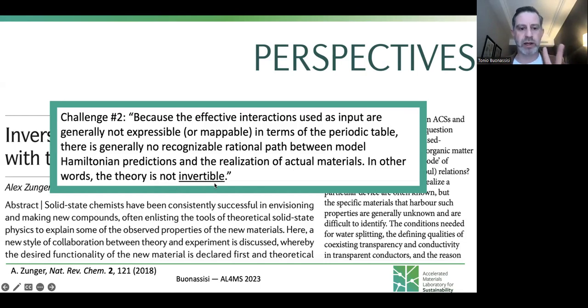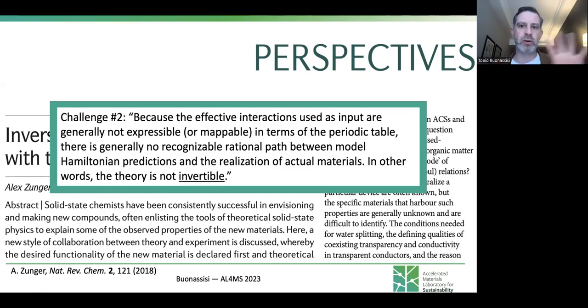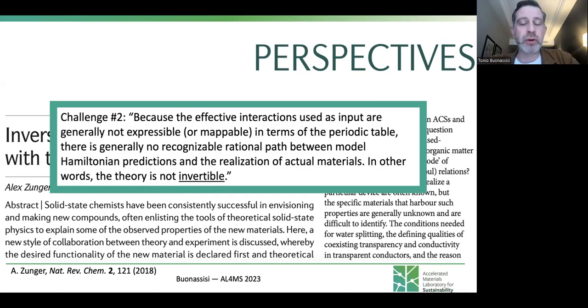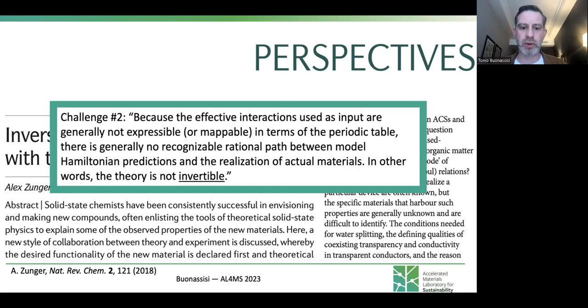The second big challenge is that many materials representations are not invertible — meaning you can put information into an algorithm and compress it, but trying to get the information back out is difficult. Think of a CIF file: it will have a different number of rows depending on the number of atoms in the unit cell, so there isn't a standardized input file format for the algorithm. Coming up with an invertible crystallographic representation that satisfies general inverse design is a major challenge.